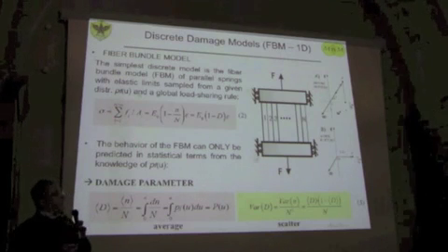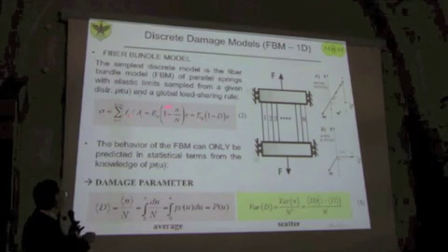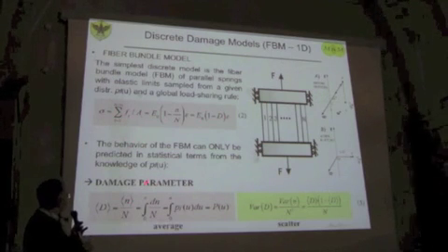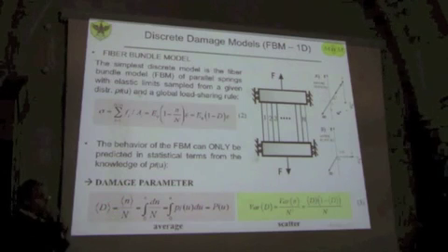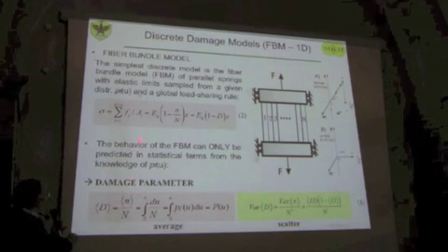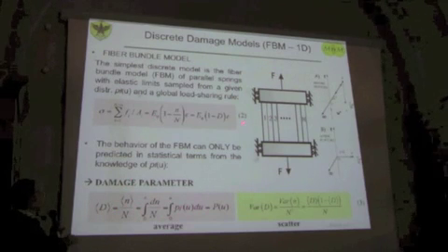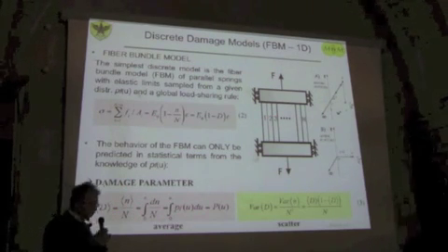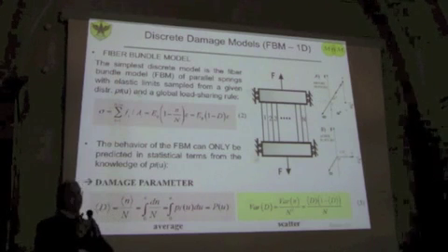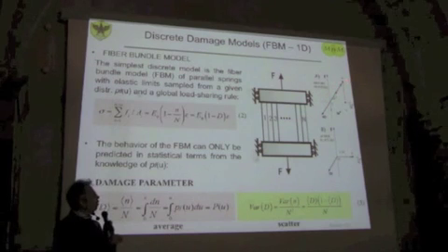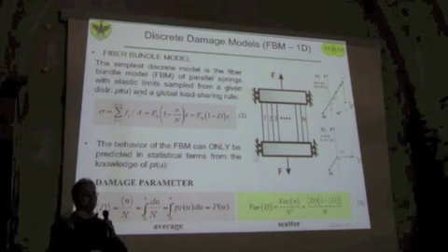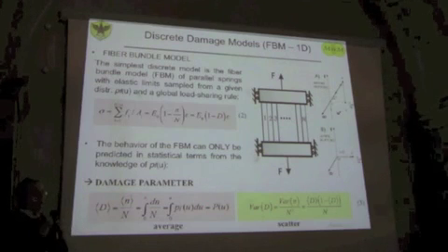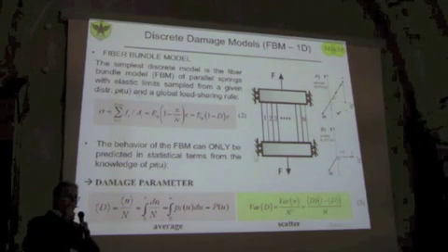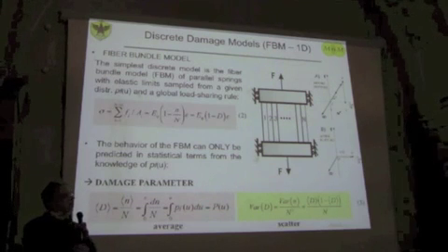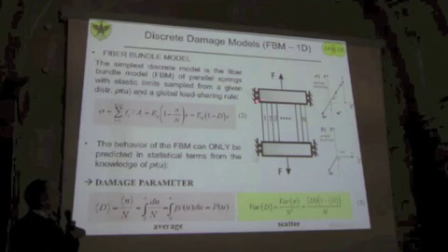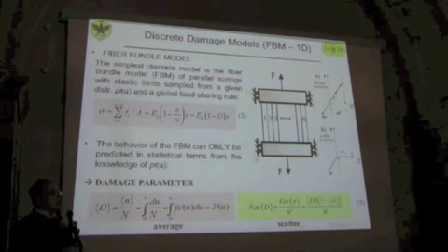Now, for instance, if we try to apply the Kachanov model, it takes this form, and you are immediately able to derive the mean damage parameter as an integral of the distribution of the critical strain of these links. These links are simply elastic elements that, at a certain random threshold, break down. What happens? You have a global sharing rule, so the load that is not taken by the broken links gets redistributed evenly over the surviving links.